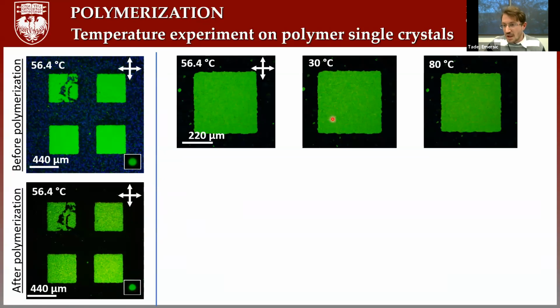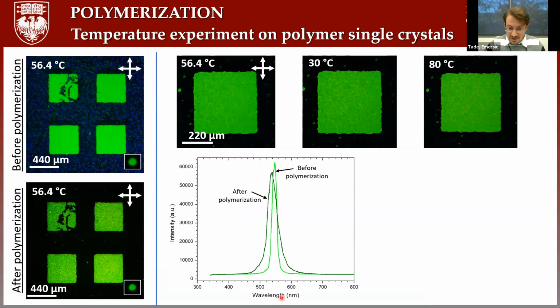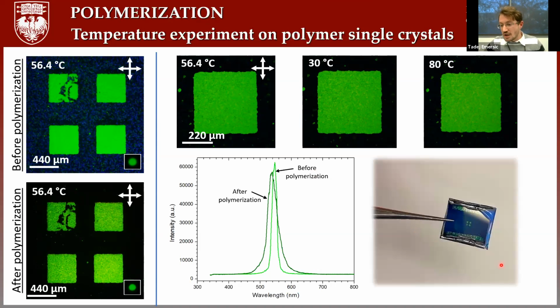After that, we can play with the temperature up and down, and we can see that this single crystal structure actually remains more or less unchanged. We also measure the reflection spectrum. We can see that before polymerization, the spectrum is very narrow and sharp. After polymerization, the spectrum is a bit broader, but according to the literature, it means that the single crystalline structure was successfully polymerized, and the structure remains more or less the same as it was at the beginning. And this is how it looks.